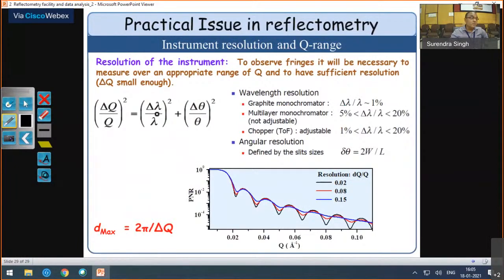Delta lambda is coming from the monochromatic beam. There is a mosaic spread, so that will contribute delta lambda. Delta theta is coming from your collimation, because you are cutting down your divergence, but still you have a divergent beam falling on the sample, and that divergence will give you a spread in the beam, delta theta.